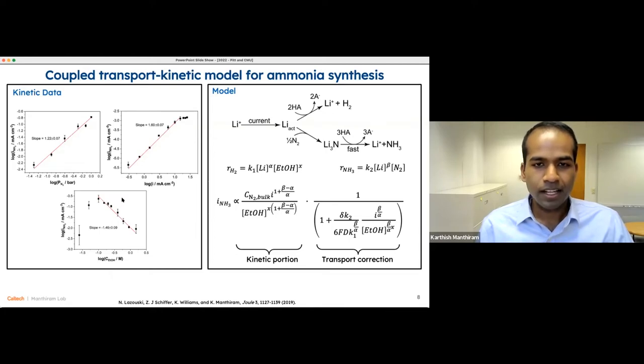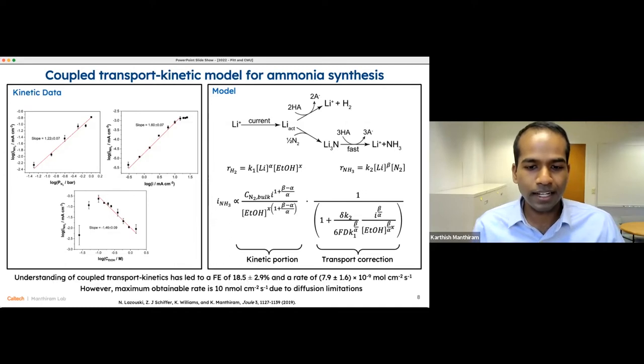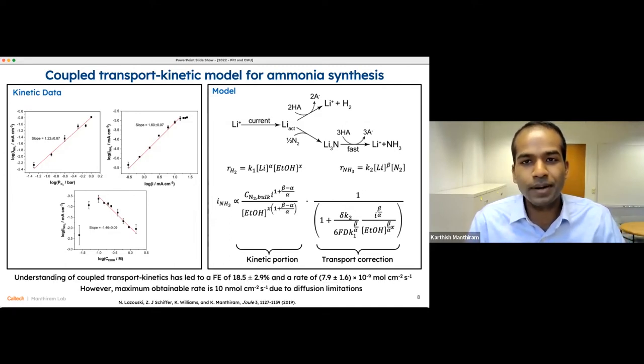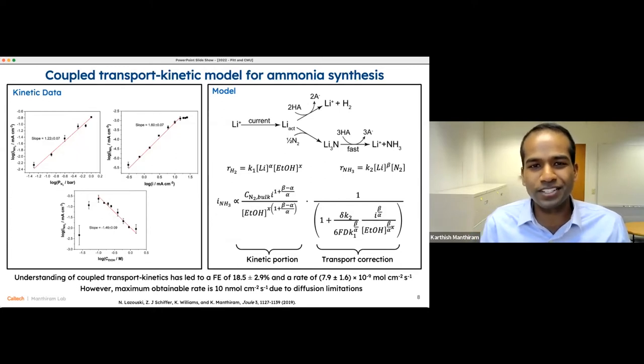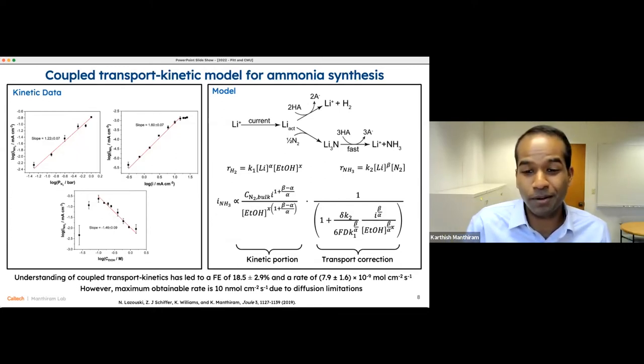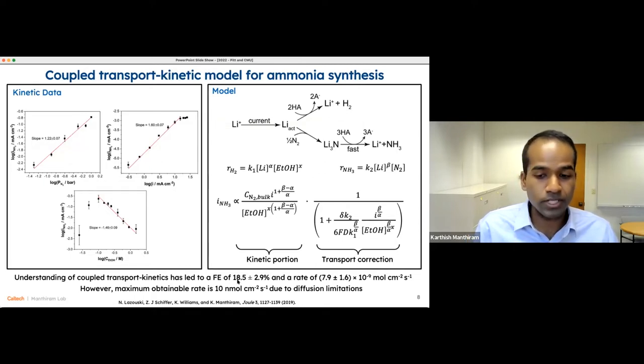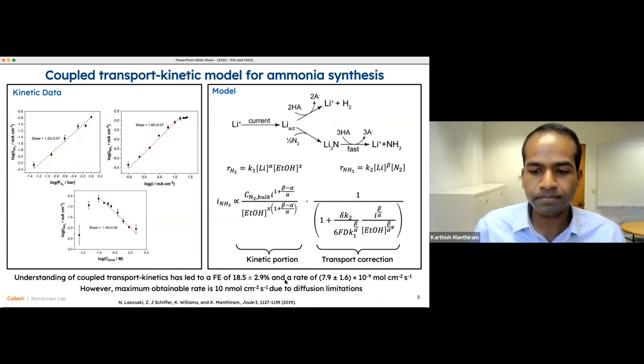Now, when we started this chemistry, the record Faradaic efficiency prior to that was 8.5%, as reported by Tsuneto et al. in the 90s. We tried to empirically optimize this chemistry over a period of several months, thinking that we could surely, 25 or 30 years later, find a better operating condition. It turns out those efforts were not productive. When we developed the model and predicted a single data point coming out of that, we were actually able to double the Faradaic efficiency in a single experiment. So we were able to get up to just under 20%. So now 1 in 5 electrons approximately going to the right place.